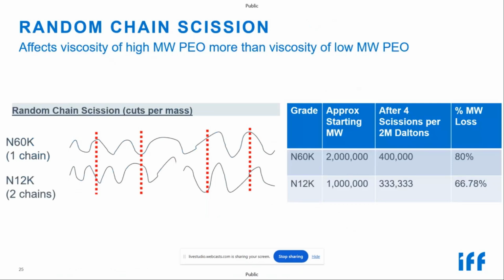All right. Auto-oxidation is random chain scission. We're not talking about cleaving at the end of a chain and creating tiny individual monomers. We're talking about randomly cutting the chain somewhere along the chain, without truly understanding exactly where. It's going to just be random. What I'm showing here is that the chain scission rate is going to impact the observed solution viscosity of higher molecular weight chains more so than lower molecular weight chains.